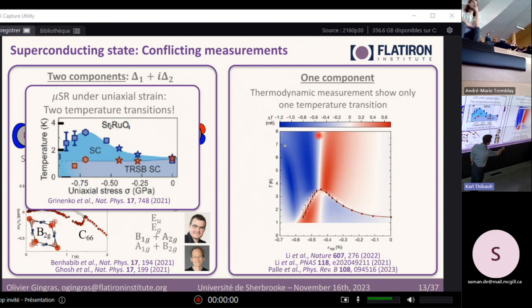But here there's absolutely no second transition where you would expect it from the μSR. And so this is very, very strange. People tend to believe thermodynamic measurements much more because they're direct measurements of what's going on, while μSR is extracted in a bit of an indirect way. And yeah, there's a lot of discussion about what's going on, because time reversal symmetry was also believed for 20 years to be present in this material.